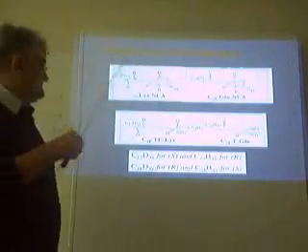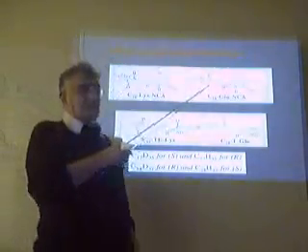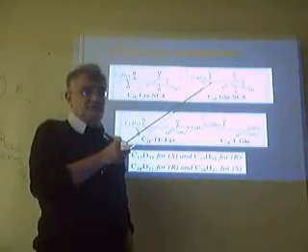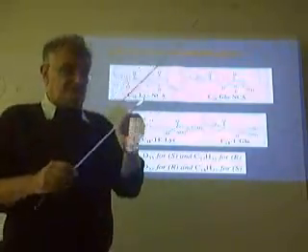Because if you add an air-water interface, yeah. And this way, you could engineer that. If you go to the ester, where you don't form that, what happens is that these hydrocarbon chains have a very high tendency to form a herringbone, and the herringbone between these chains takes place along a glide plane.